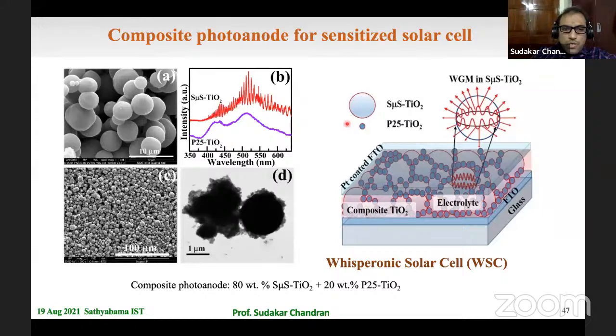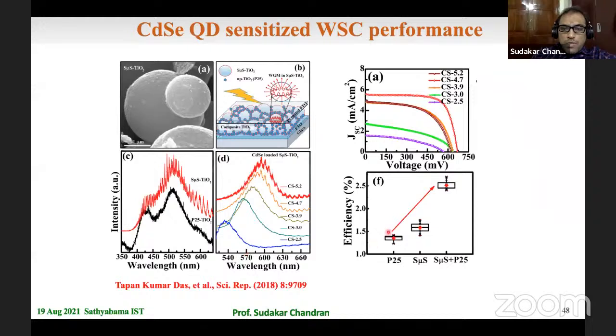And in our structure, we used these micron size spheres in combination with the mesoporous TiO2, so the micron size spheres can produce whispering gallery modes, whereas the mesoporous TiO2 provides a conducting pathway. Like the one I show here, this is a sphere and nanoparticles are present on the surface, coated. So this is the typical structure you will see. In such a case, we found that the efficiency can be increased by several folds. And this is one of the data from the cadmium selenide quantum dot sensitized solar cell.